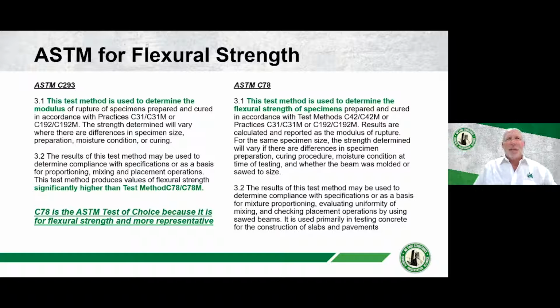So I mentioned earlier about the ASTM testing that's done for flexural strength. There are 2 tests that are used in the field. There's the ASTM C293, but the ASTM C293 is actually a measurement for modulus of rupture, which is similar to flexural strength, but a little bit different. The ASTM C78 is the test that's specifically designed to determine the flexural strength of mortar systems. The difference is because this C293 test is for modulus of rupture, it loads the specimen very, very rapidly. And because of that, what happens is that the results you get for the exact same material in the exact same beam is significantly higher.